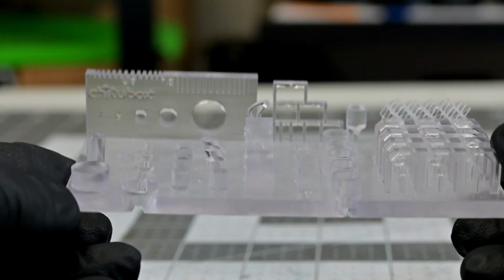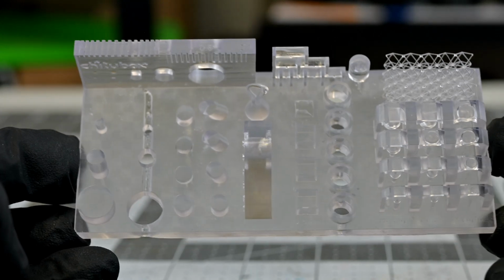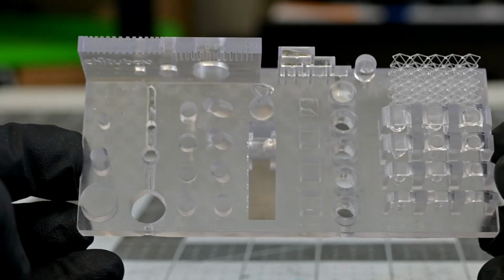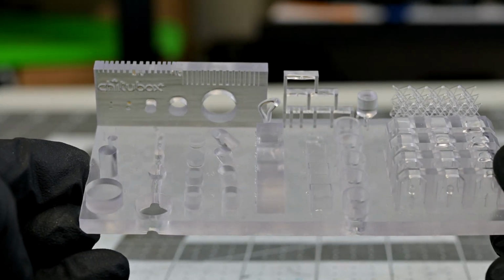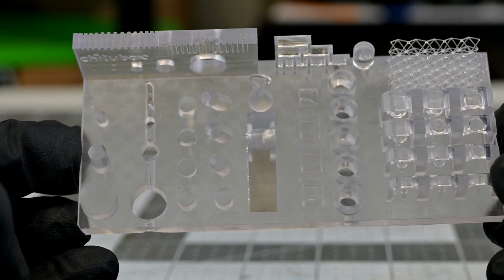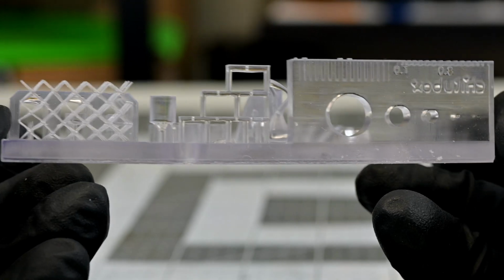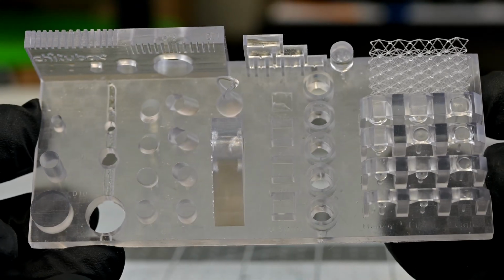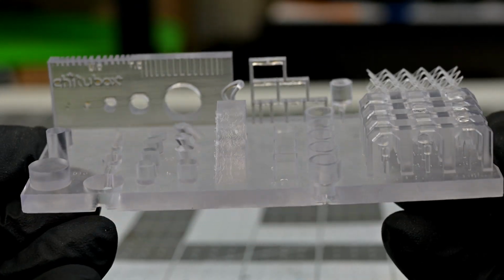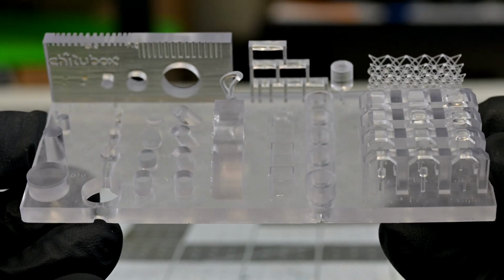Looking at the Chitubox torture test, I'm seeing very impressive results. Like the Creator Tough, the Super Clear resin only started struggling at the thinnest 0.2mm gap in wall thicknesses, but it printed the lattice test perfectly. It failed all 4 light supports, and failed 1 of the medium support tests, but the rest passed. Overall, this is also a great showing from the Creator Super Clear.